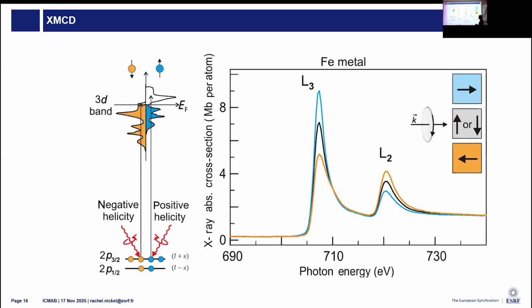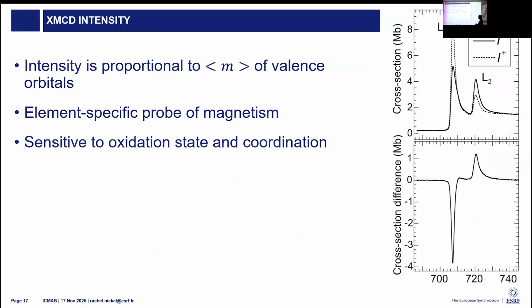And we see the difference in the filling of the density of states as dichroism by measuring left and right polarized and taking the difference. So the intensity of the dichroism is proportional to the magnetic moment. Just like standard XAS, this is an element-specific technique, and it encodes the site and the bonding information as well.